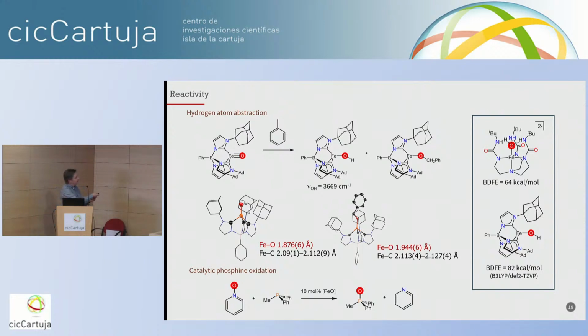So I think the most interesting reaction it did was it can react with toluene. So it abstracts a hydrogen atom from toluene to make this hydroxide. This is the impurity we see in the Mossbauer spectrum. And what happens then is actually it can also couple with the radical to make some of the alkoxide complex here. So this is a sort of a different type of reaction.